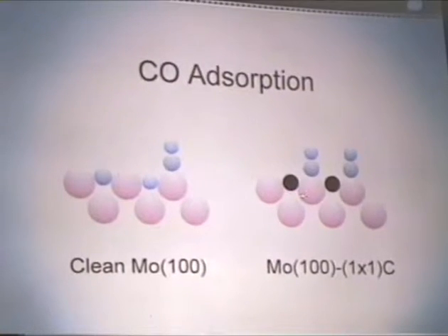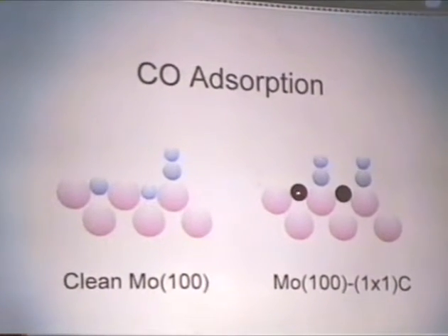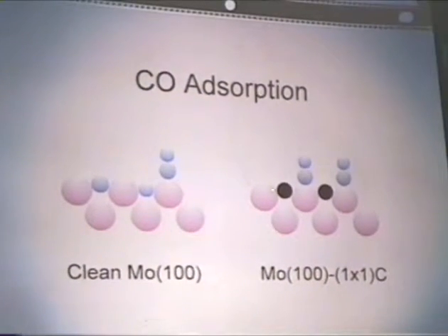However, if they then take a clean moly surface and carburize it by cracking ethylene at 500 Celsius, they obtain carbide atoms, which they propose to be in these same four-fold hollow sites. So this black is a carbon atom in the form of carbide on the surface. And what they obtain then is, once the surface is saturated with carbide atoms, they only get molecular CO off the surface. And so this serves as a possible differentiating factor between parent metals and transition metal carbides.